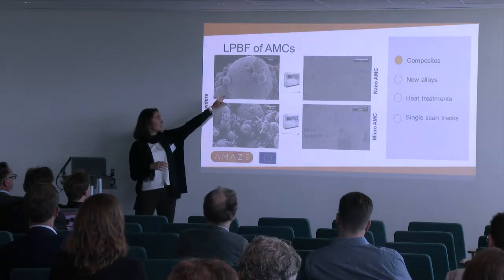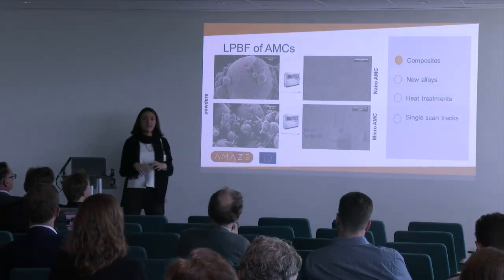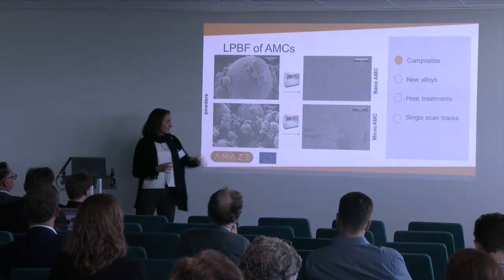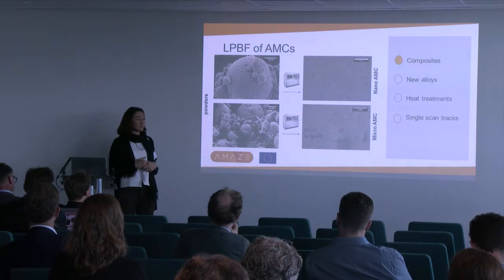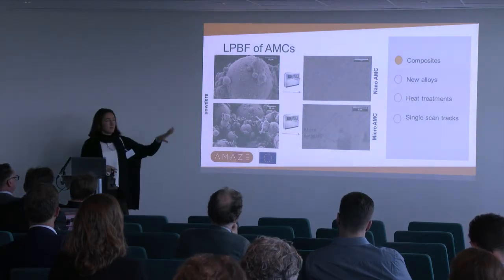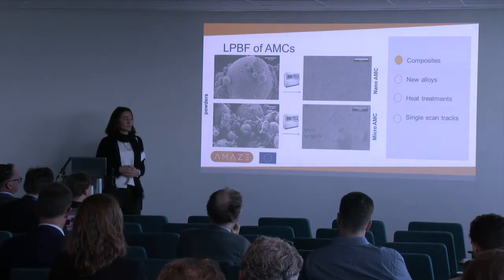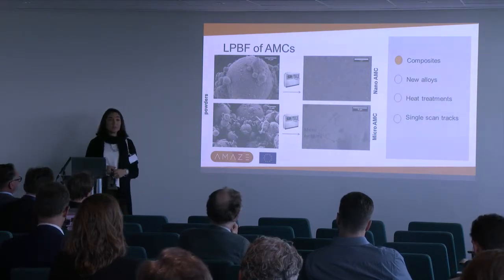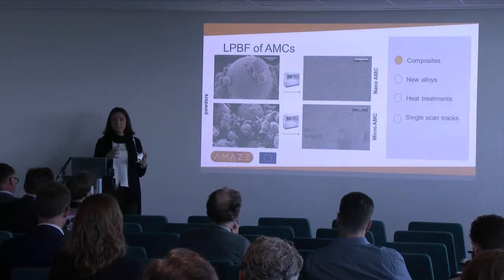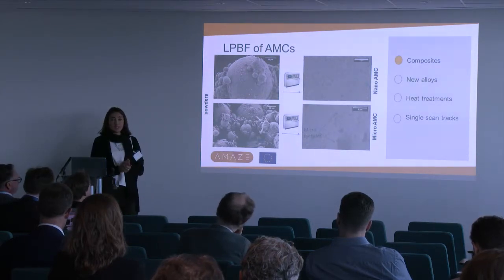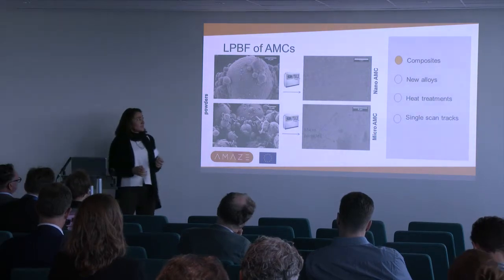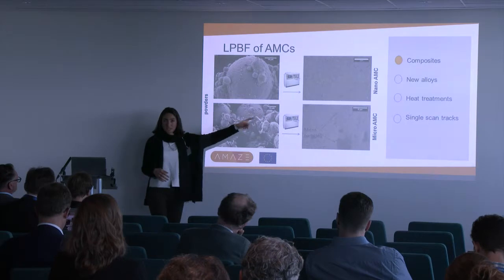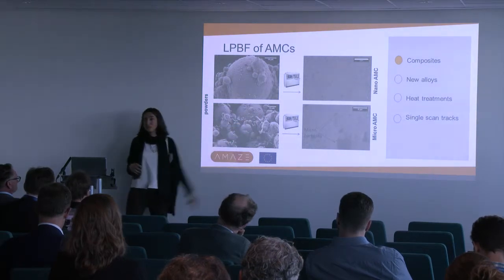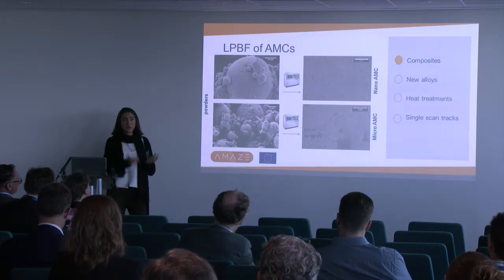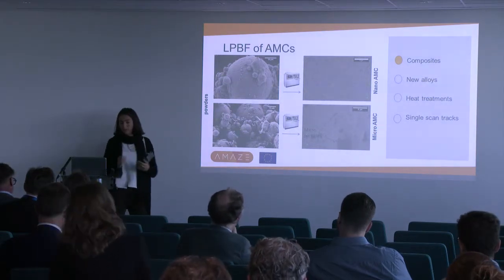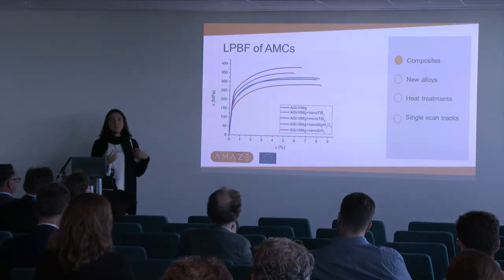We have aluminum particles here, and all these dots, I don't know if you can see it really fine, are nanoparticles. And here we have these irregular shapes, which are microparticles. We simply mix the powder, we put it in the EOS machine, and what we obtain are microstructures such as this one. In both cases, by selecting the suitable parameters, we could obtain dense and crack-free composites. In the nanocomposite, it is not possible to see the particles. In the microcomposite, they seem well homogeneously dispersed and not, for example, agglomerated in the bottom part of the melt pool or whatever. So we went to see the mechanical properties.